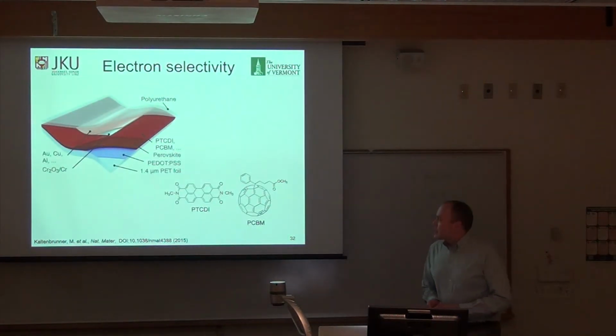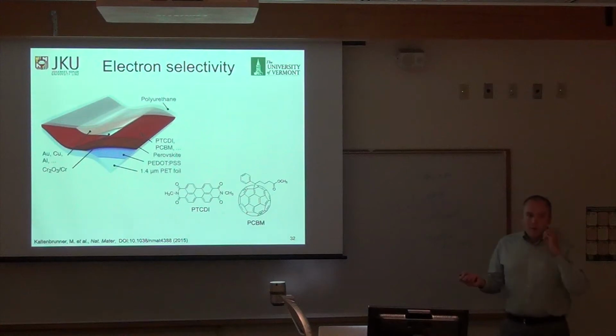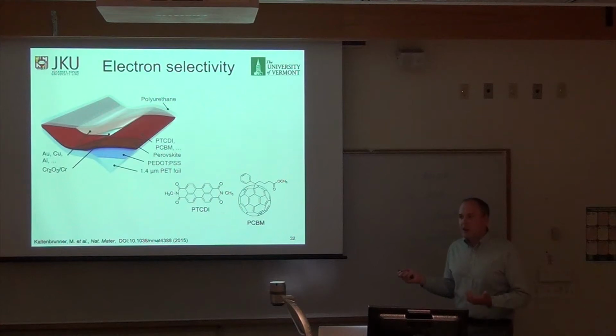So what do we do about electron selectivity? Well, because we come from an organic solar cell background, we said, oh, this is the best electron selective material we know. We tried it - it works, but it itself is very air unstable. So we pretty much ditched it right after we showed that it works.